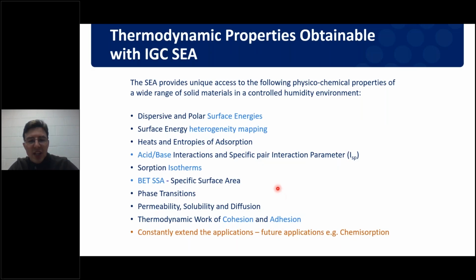So on this slide, you can see a summary of all of the things that we can determine using this technique. We can determine the dispersive surface energy, the polar surface energy. We can map it as a heterogeneity. That's been mentioned previously in dynamic vapor sorption. We can also measure the heat, the enthalpy and entropies of adsorption using this technique. We can also get a few other things like the surface area, the acid and base interactions of my surface, monitor phase transitions. We can look at permeability and solubility and the thermodynamic work of cohesion.